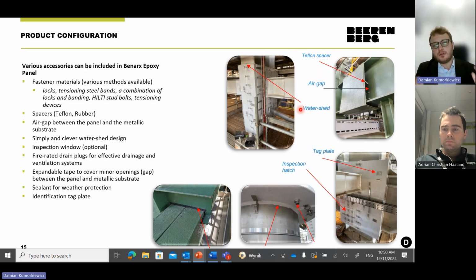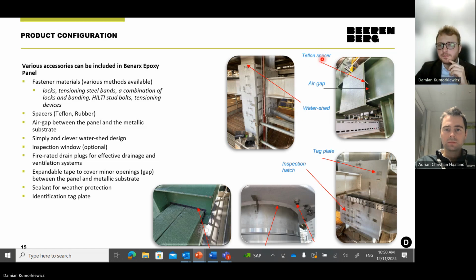When it comes to the details of the product configuration, we have several accessories. Not all of them are mandatory. For example, you have a Teflon spacer. This is the spacer between the metallic substrate and the panel itself for supporting functions. You have an air gap that creates a small space for the char expansion in our panel system, and it also gives you very good ventilation. In case of water ingress, the water will not be stuck there, and it's a very good solution to mitigate CUI. Watershed, that's the roof principle on the top section of the panel, just to let water run off. Each panel segment is equipped with an identification plate or tag plate.